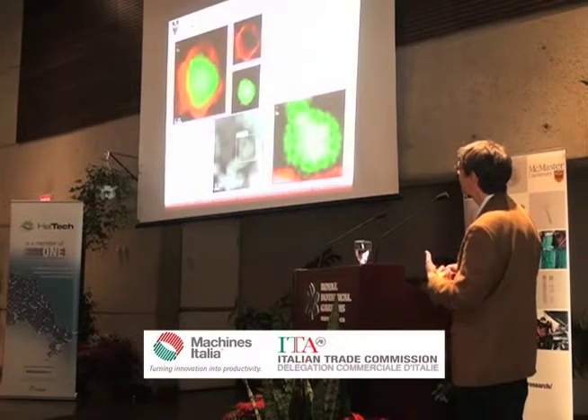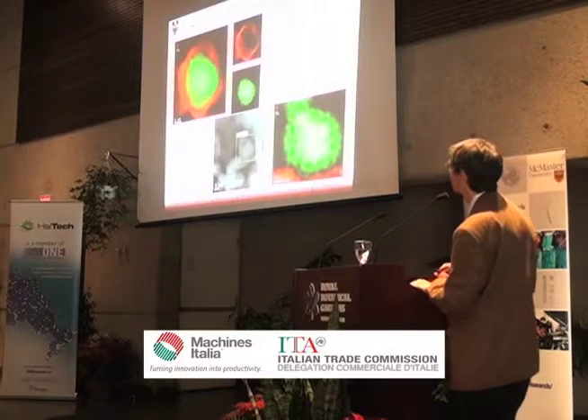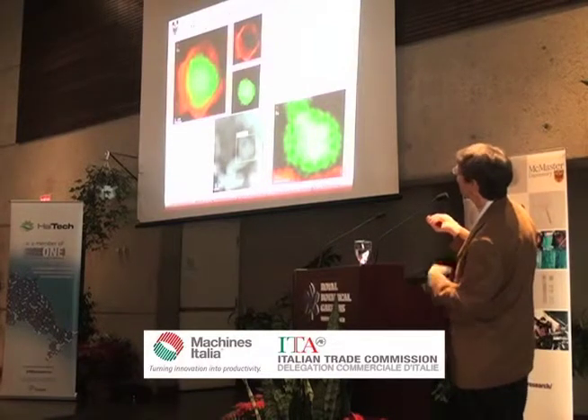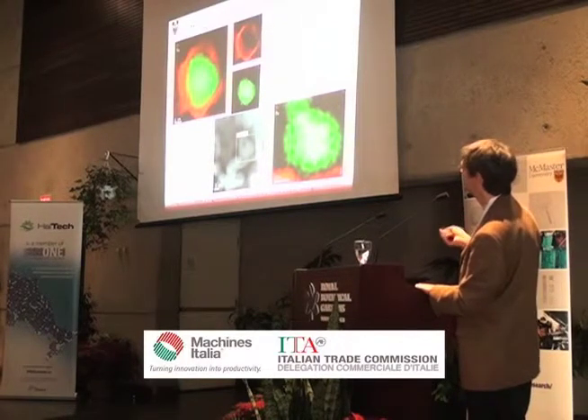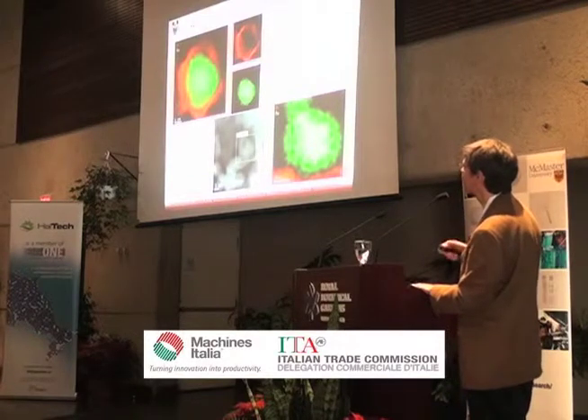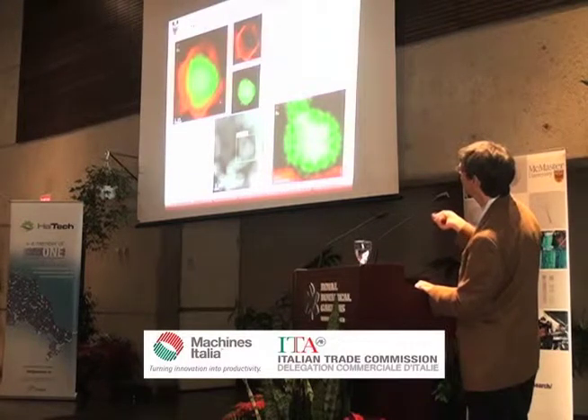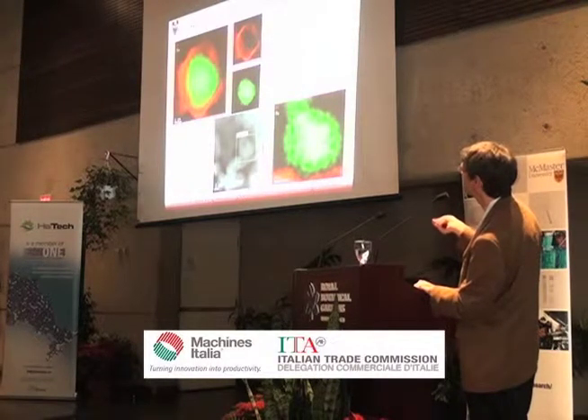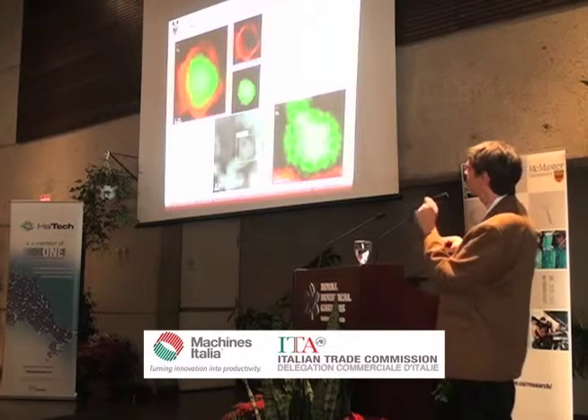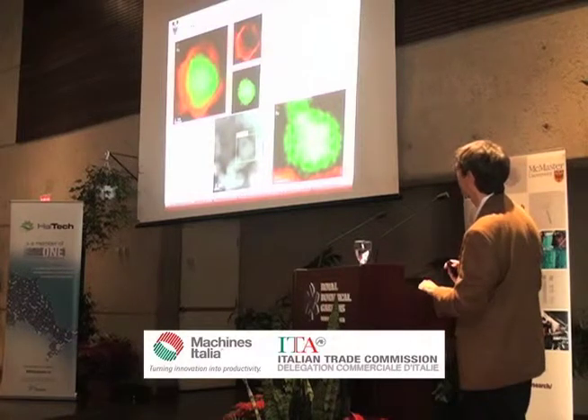And then in addition to that, you can actually not simply show images, but we can do chemical analysis. And I don't describe how we do it, but just take my word for it. In this case, I show one of the nicest ones we obtained, where we can see that it is a platinum ruthenium. So ruthenium is an expensive metal, but it has advantages compared to platinum for fuel cell applications. And in this case, we can show that we have a platinum shell on the surface of these particles, just by the color. So platinum is in red, and ruthenium is in green. You can see we have almost one atomic layer, or maybe two atomic layers of platinum on the surface. So you waste really very little amount of platinum, so we can minimize the cost of these fuel cells.